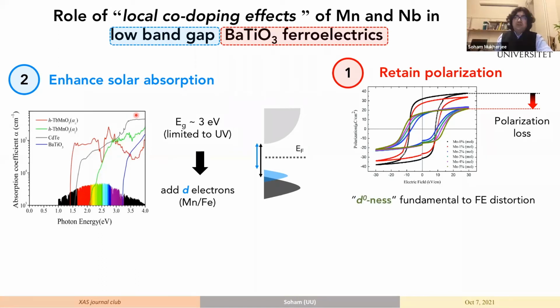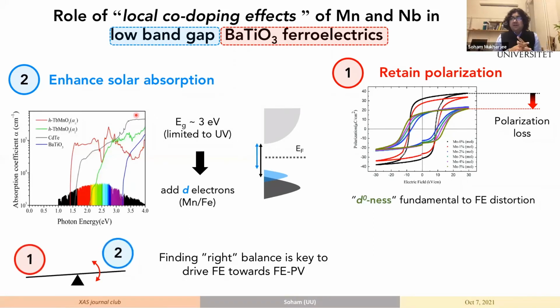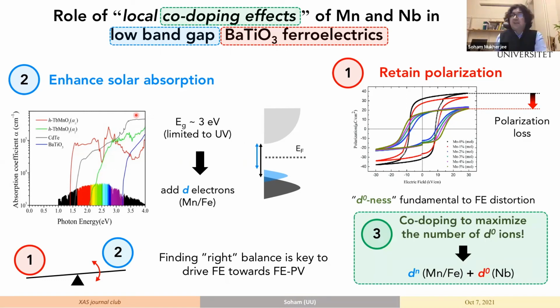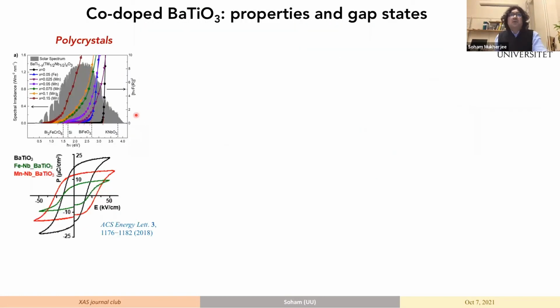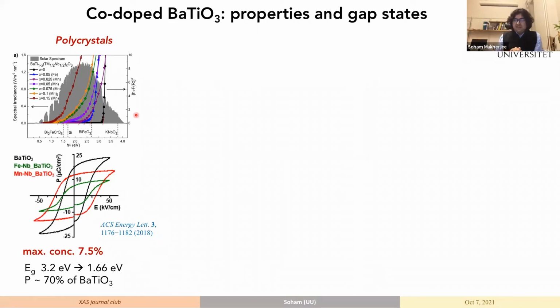So the idea was to do a co-doping, which was conceived at IISc Bangalore in Professor D. D. Sarma's group, and I was not involved in that part of the project. I came into it a bit later. The idea was to co-dope the system with both d0 systems and dn systems so that there is a balance between the two ions. Polycrystals were made with both iron and manganese, and it turns out that manganese performed better than iron. We would come to why that is in a second. For 7.5% co-doping of manganese and niobium, the band gap was substantially reduced and the polarization was retained at about 70% of pure barium titanate.